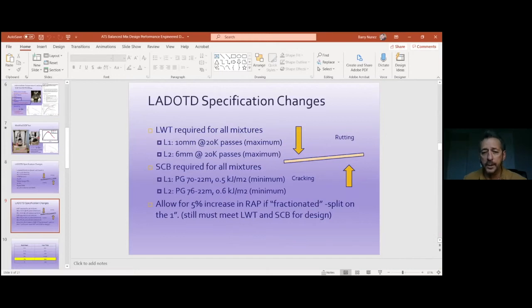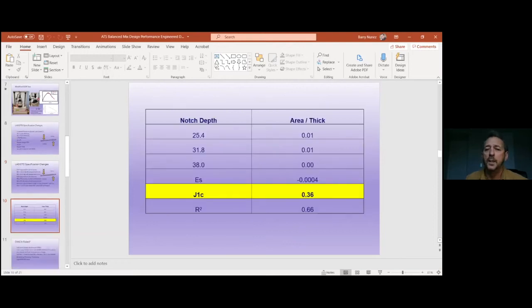Once again, though, when we did get to increase the RAP, we did have to fractionate. At least, we didn't have to fractionate real fine. We had to at least take off the top 1 inch. And that was a good move. And we finally got the state to agree that we didn't have to do this ahead of time. We could put a 1 inch scalping screen on our RAP in direct line on the plant. So I'm going to jump right into my results.